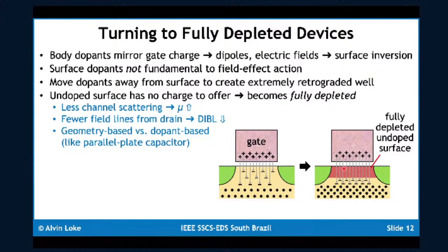You also don't have field lines, in the absence of charge here, to terminate fields that come from drain charge. You don't have as much field lines terminating from the drain here, which means that your DIBL is reduced. Basically, what we are essentially doing is migrating from a dopant-based structure to a much more geometry-based structure where we essentially have built like a parallel plate capacitor device.